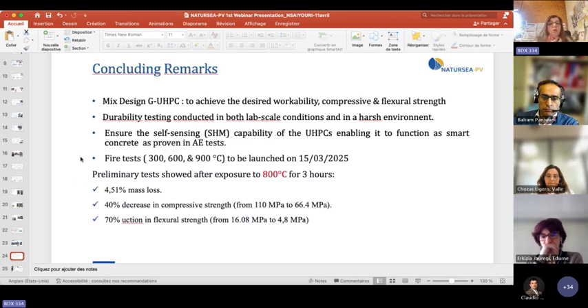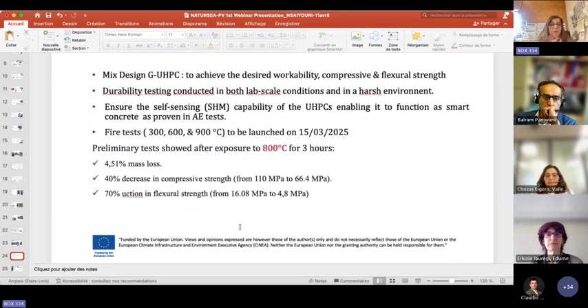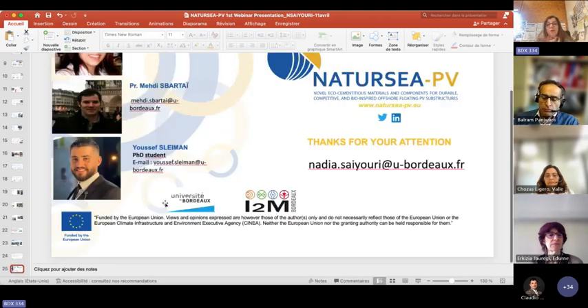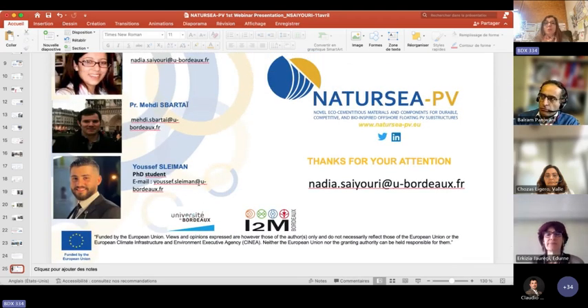We are running, or we ran, just some preliminary tests in fire, in a condition of fire. At least 3 hours at 800. We have an oven to expose our samples, and we will follow the mass loss and the compressive strength, and also the reduction of flexural strength after exposition to these high temperatures. So thank you for your attention, and if you have questions, I will be happy to answer.